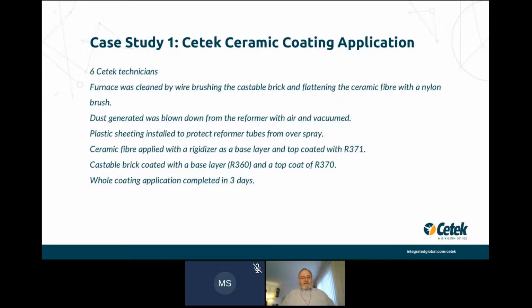The ceramic fiber modules tend to be rippled on the surface when they're new. After we've cleaned the friable fiber away from the surface, they tend to be a little flatter rather than rippled. So there's less of a corrugated surface on the fiber. The dust that we generated, we blow it down inside the unit and then vacuum it up. We put plastic sheeting to protect the reformer tubes, the catalyst tubes, from overspray so that they remain clean.